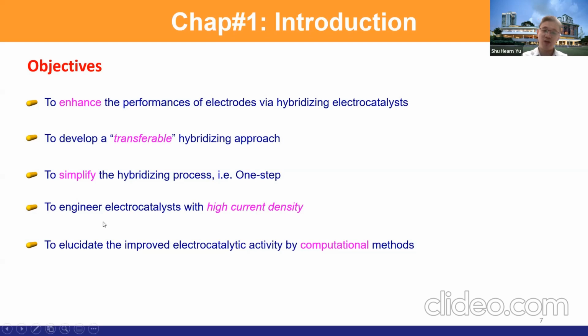So I need to find a way to make a very robust or durable catalyst. As such, it can withstand high current density and yet have very good activities, meaning it only requires low overpotential to achieve high current density, for example 1 ampere per cm square. And to elucidate the improved electrocatalytic activity by computational method.